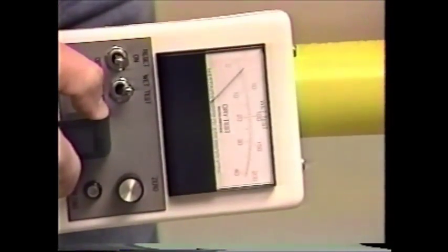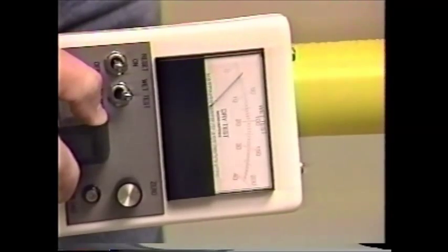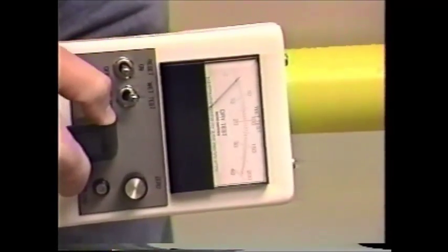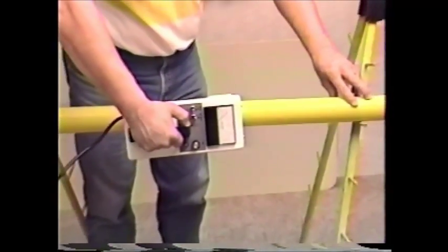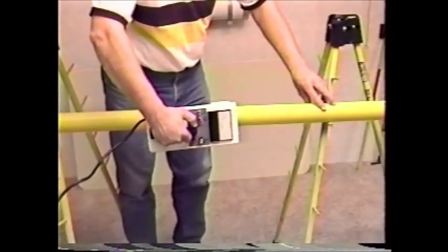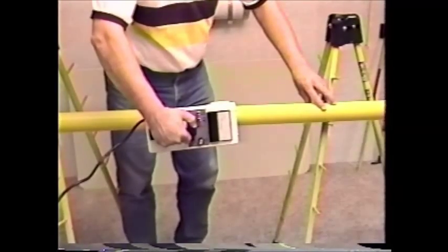For the most critical results, the stick should be rotated 180 degrees and checked again. While the tester will sense a defect on the opposite side of the tool, the maximum reading can only be obtained by rotating the tool. In this case, the tool measures approximately 20 microamps and passes the test.